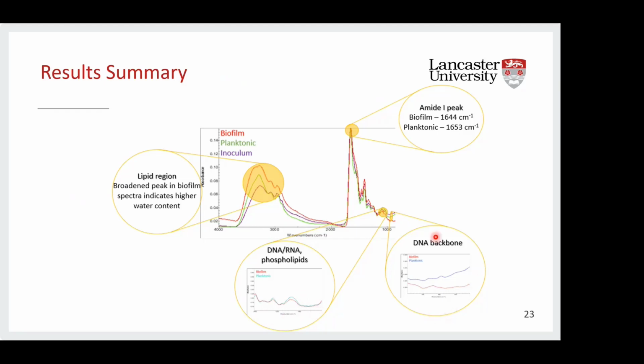Finally, we have a very interesting occurrence in this DNA backbone peak, where 2 key peaks in the planktonic sample seem to coalesce in the biofilm sample. And what this is actually indicating is that there's a fundamental change occurring within the bacteria of the biofilm.